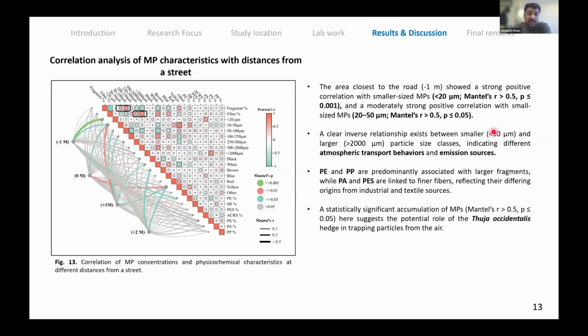Now we have the correlation analysis of microplastics, and we have seen that the area closest to the road shows a strong positive correlation with small particles less than 20 micrometer and a moderately strong positive correlation with particle sizes of 20 to 50 micrometer. A clear inverse relationship has been observed between particles less than 50 micrometer and particles larger than 2000 micrometer, indicating different atmospheric transport behavior and emission sources.